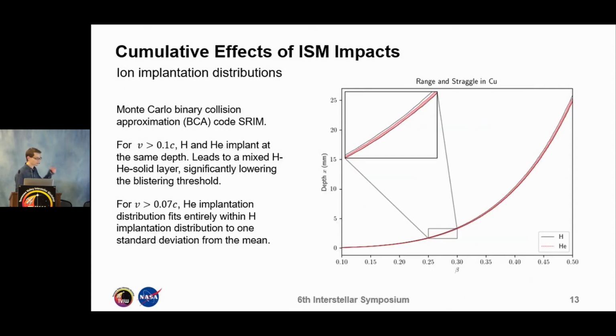So in order to find implantation distributions of ISM gas atoms at relativistic speeds, we use a Monte Carlo binary collision approximation code called SRIM. This predicts that at velocities greater than 10% of the speed of light, hydrogen and helium will impact at the same depth, as we just talked about with the beta block stopping. This leads to a mixed hydrogen, helium, and solid layer, which can lower the blistering threshold, since the transport behavior of implanted gas below the surface is different.